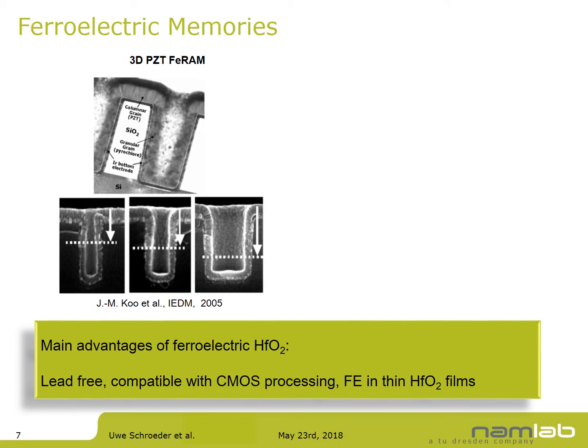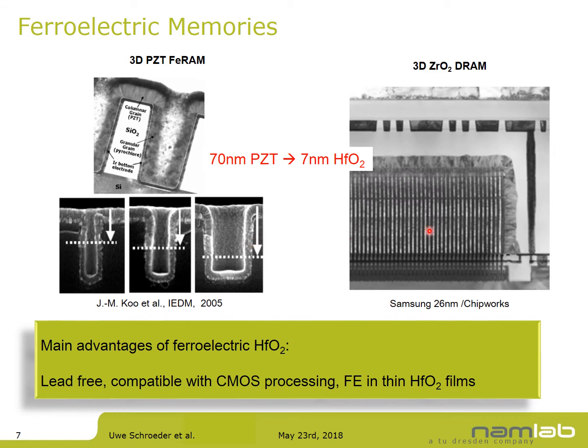There is a clear advantage compared to currently used lead zirconium titanate (PZT) FRAM devices. Current market devices are planar, but for three-dimensional structures, PZT at around 70 nanometers is very difficult to scale to smaller ground rules. By contrast, a current DRAM structure is a 26-nanometer structure where one capacitor spans two of those white lines. A 7-nanometer hafnium oxide layer has a clear advantage over the much thicker PZT layer for introduction into these highly scaled devices.